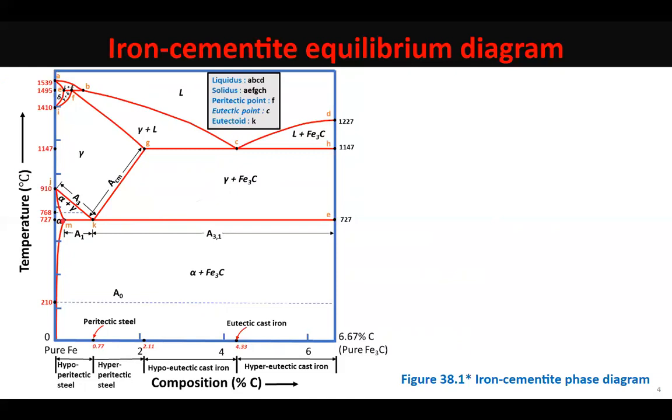But ideally or theoretically speaking, if an iron carbon alloy has carbon in the range 0 to 0.02, then on reaching 727 on cooling, it would have only ferrite in it, no austenite. But practically for all other iron carbon alloys, austenite phase would always be there on reaching 727, and this phase would always be of 0.77 percent carbon. So virtually all iron carbon alloys, all steels, all cast irons would show the eutectoid reaction.